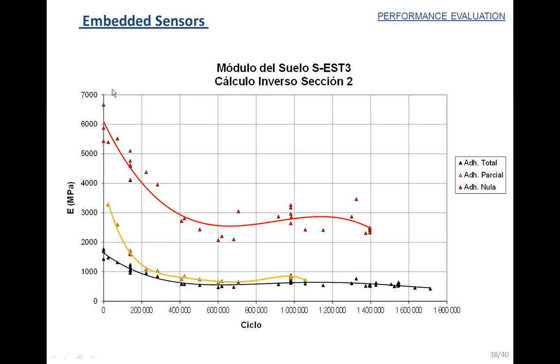So we used that program, and we also introduced the asphalt strain in order to do the back calculation. So we did back calculation in order to fit deflection, and at the same time in order to fit asphalt strain under the pass of the vehicles. So when we do that, the good thing is that bonding between the two layers, asphalt layer and cement stabilized layer, that bonding strongly depends on the strain that we measure at the bottom of the asphalt layer. But probably I should say the opposite. The strain that we measure at the bottom of the asphalt layer is highly dependent on that bonding between the two layers. So we could back calculate bonding.